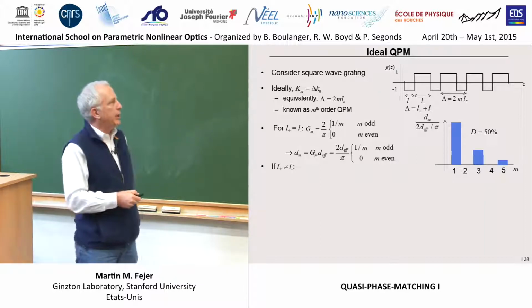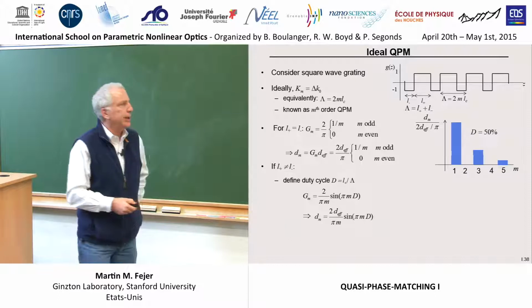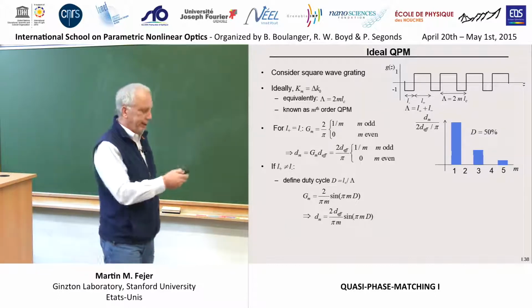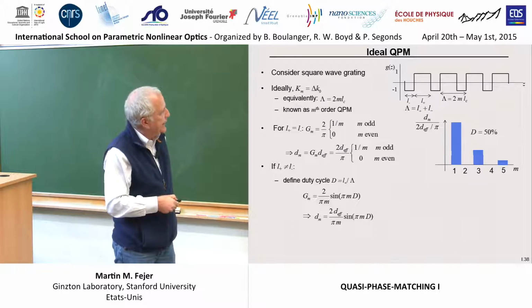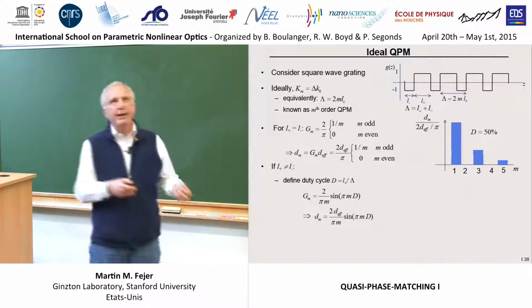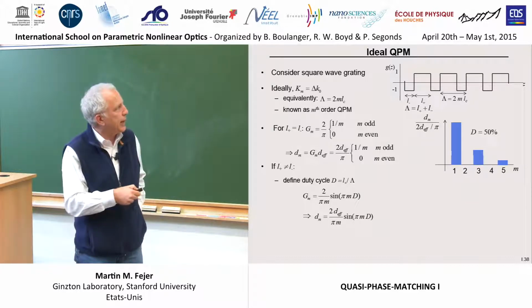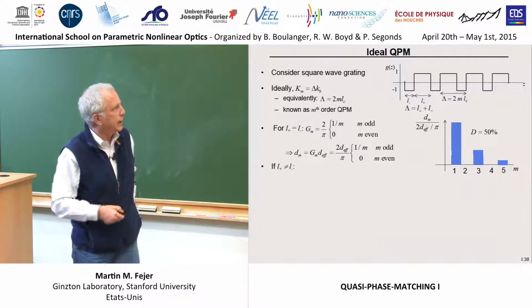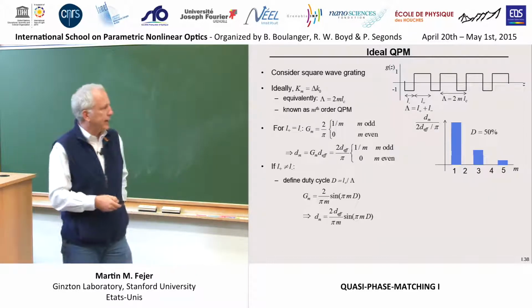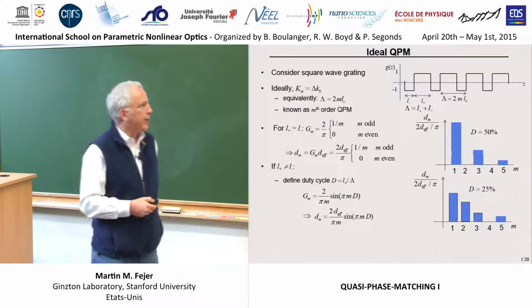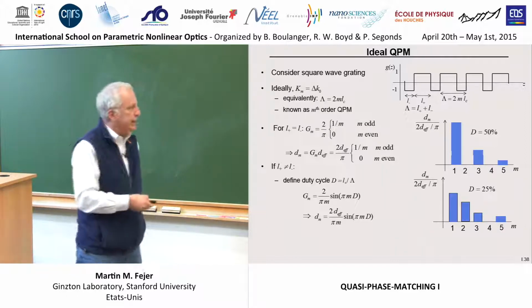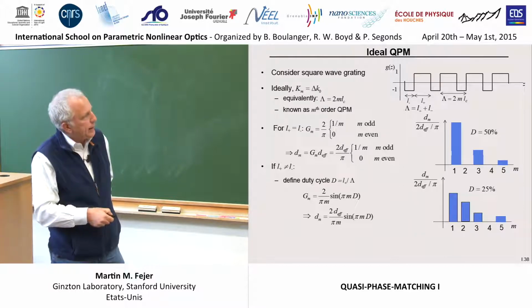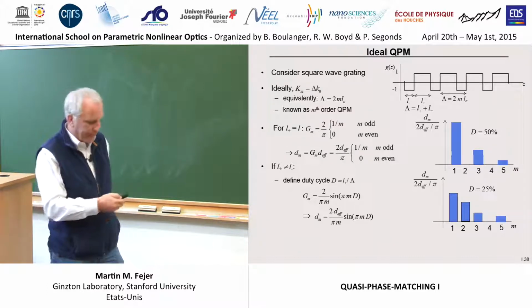If the lengths are unequal, if L plus is not equal to L minus, if you do your Fourier series carefully, you find that instead of just 2 over pi m, there is a factor sine of pi times m times the duty cycle. That is the ratio of the positive thing to the total period. And the implication of that, for example, for a 25% duty cycle grating, is that you can now have non-zero, or sometimes vanishing, even orders, just according to this sine pi m d over m factor.